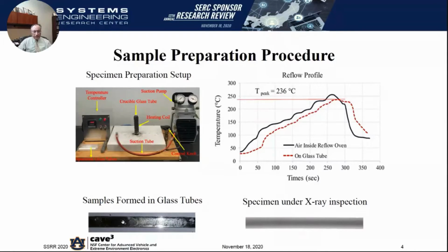And the way we do that is by using glass tubes. So we melt the solder alloy that we are trying to study. Most of these are advanced doped solder alloys. That's what the industry is migrating to for a number of reasons. And these are starting to appear in many of the commercial parts as well. So we have worked with a number of companies to actually procure these alloys. We melt them in this crucible that has a heating coil around it.